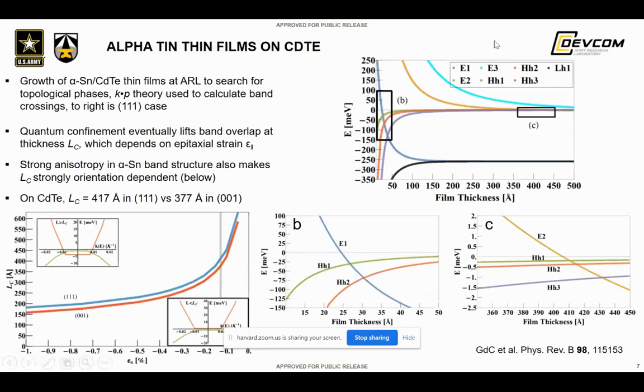This is shown in this plot of the energy band structure, the band gap energies, as a function of film thickness. You can see as you go to large thicknesses, you have a topological surface state which is well below the gamma 8 conduction band. At these thicknesses here, there's a region where the bands overlap, and you have a Dirac semi-metal for thicknesses that are greater than around 400 angstroms in the case of 111 strained alpha tin. As you go to smaller thicknesses, you can see that the conduction band starts to lift away and uninvert the band gap crossing, and you transition to a 3D topological insulator due to the quantum confinement effects.